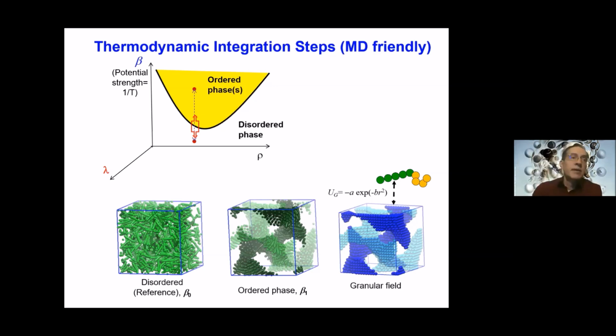Yeah, I think that idea goes along with some of the things we are trying. But to clarify, when we use this method, say the one I'm showing here, this structure is something that forms spontaneously. So we don't anticipate this based on the molecular design. We have the molecule that happens to sometimes give this phase, but not uniquely this phase. Sometimes it could give another phase. So this was meant to discriminate between the stability of the phases. But once this structure formed, then you can use the geometry that you see to create an artificial field for this thermodynamic integration, and basically avoid this hysteresis loop. So that's a different constraint, I guess.